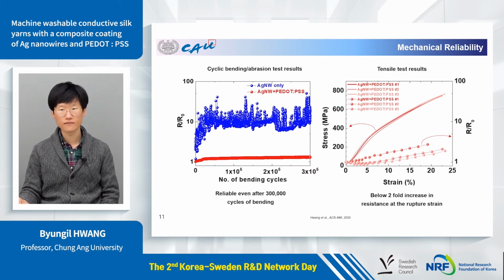So to further confirm the reliability of the conductive yarns, we tested cyclic bending and also tensile tests on our conductive fibers. The top left image shows the resistance change of the conductive fibers during the cyclic bending. That result showed that our fibers showed less than 30% increase in resistance even after 300,000 cycles of bending, while only silver nanowire coated yarn showed nearly 2 orders of magnitude increase.